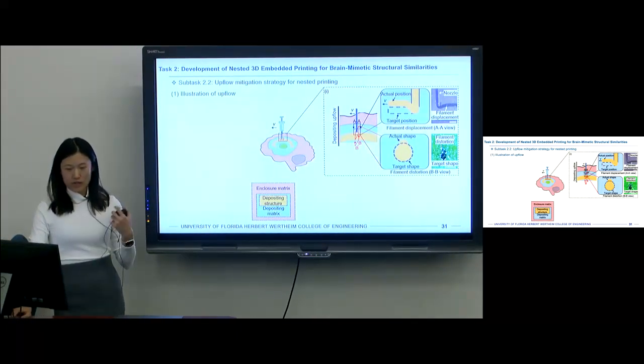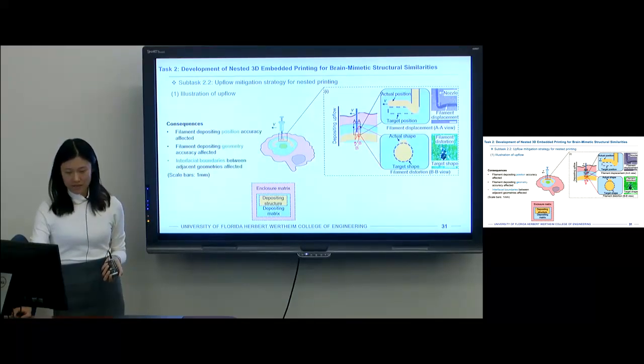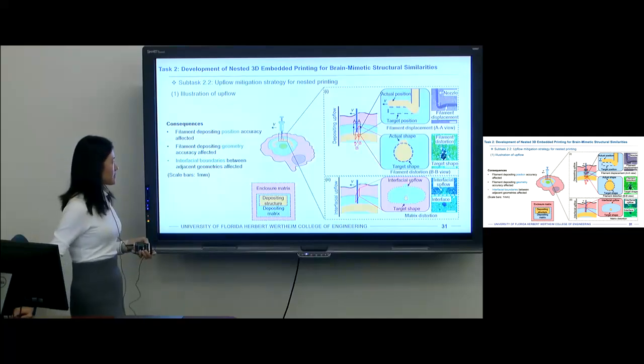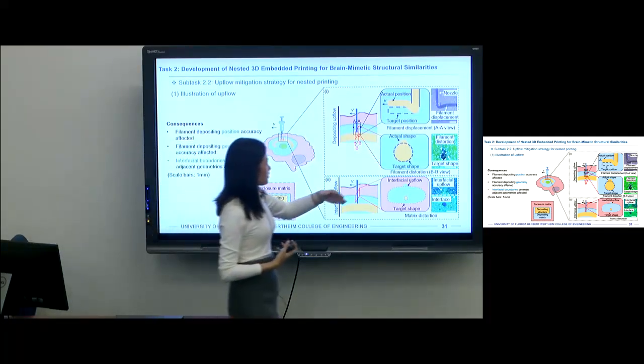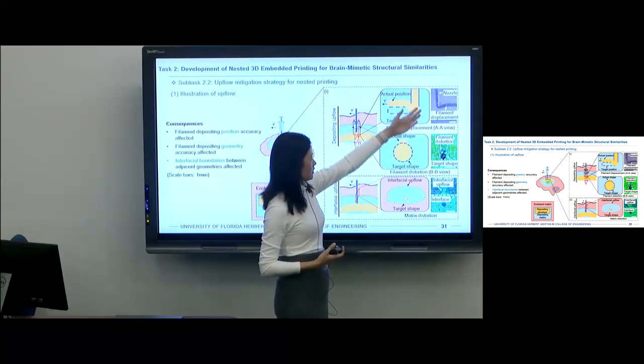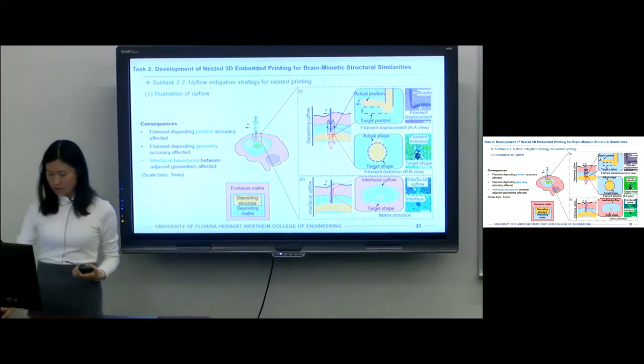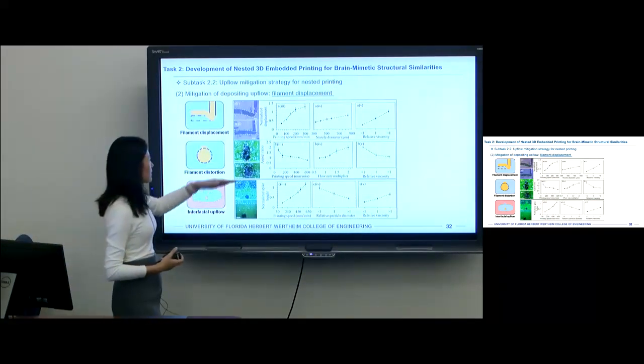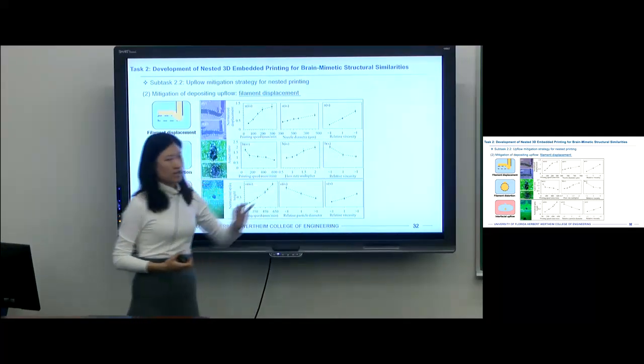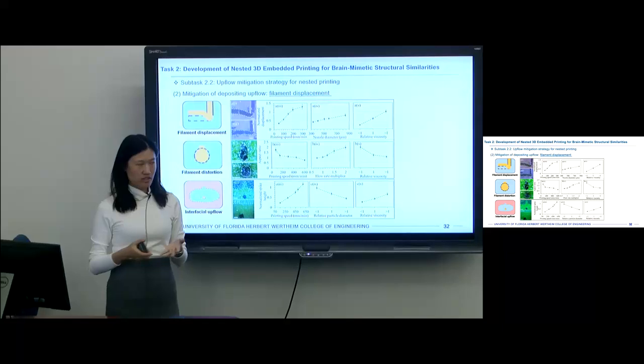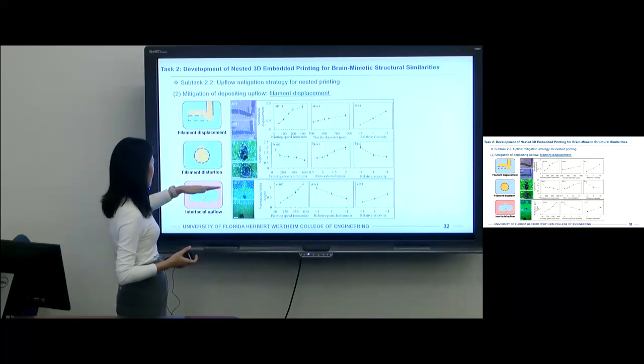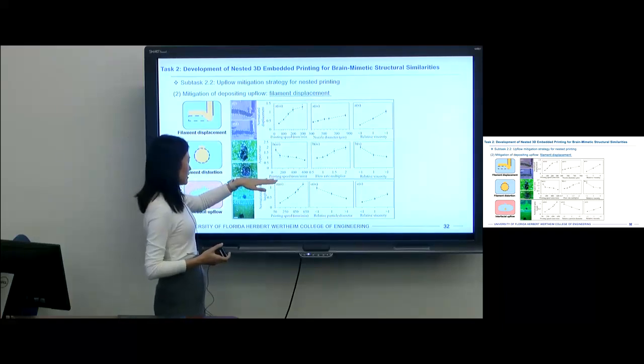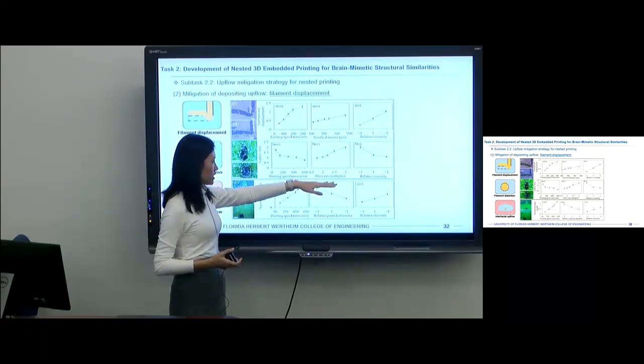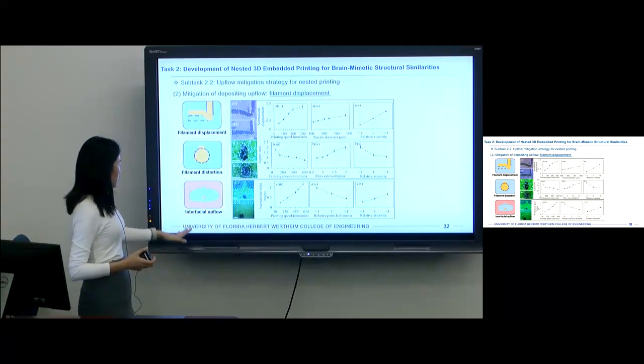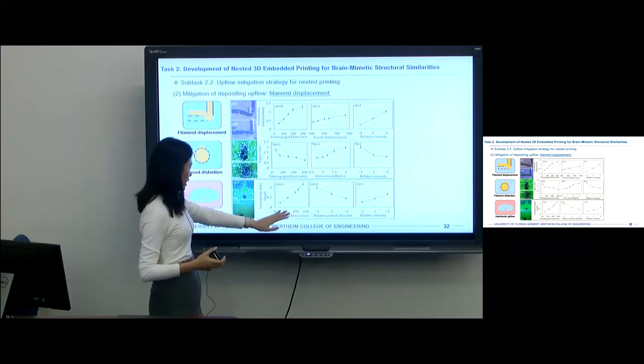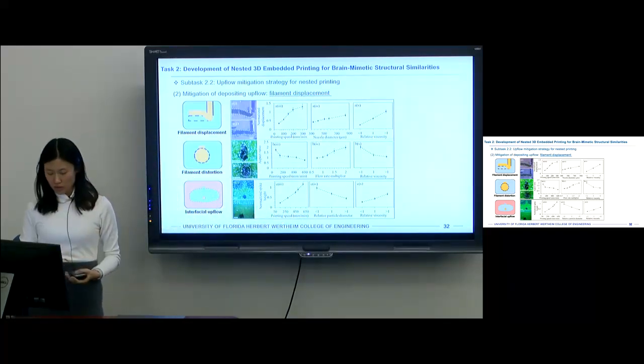So in this section, we would like to mitigate this upflow phenomenon inside of nested printing. This is the printing result in our experiment that we observed. We figured that by controlling the printing speeds, the nozzle diameter, and the relative viscosity between the depositing ink and the matrix, we are able to mitigate the filament displacement. Similarly, the filament distortion can also be mitigated by optimizing the printing speeds, the flow rates, and the relative viscosity. As for the interfacial upflow, there are also some parameters we can use to tune it and achieve the optimal results.